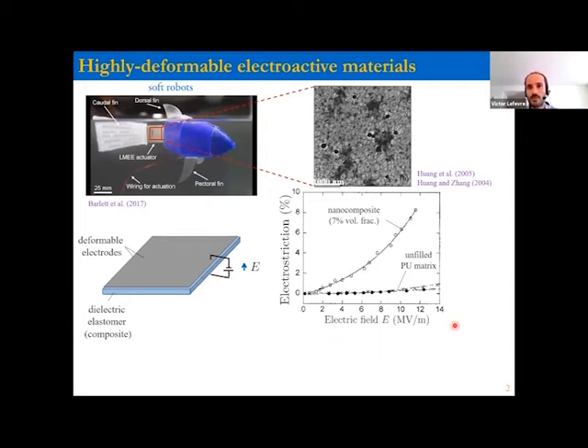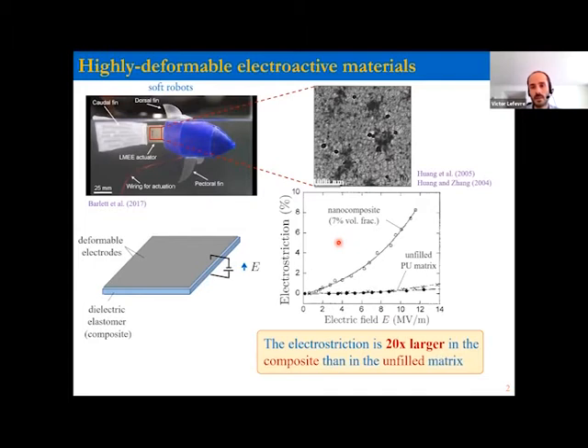It's here on the y-axis, and it's plotted here as a function of the applied electric field. There are two sets of results on this graph. The bottom results are for a homogeneous unfilled polyurethane matrix elastomer. And the top result is for a nanocomposite of this polymer with a 7% volume fraction of inclusions. That's just a snapshot of what the microstructure looks like. You can see that for a given electric field, the nanocomposite deforms a lot more than the unfilled matrix. So the enhancement here is about a factor of 20.